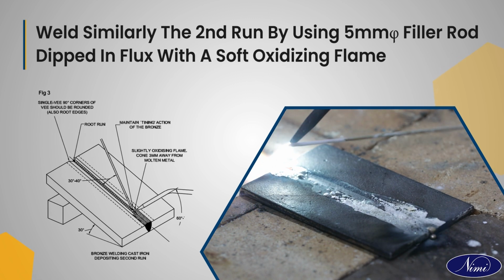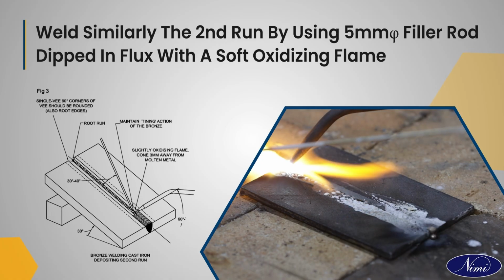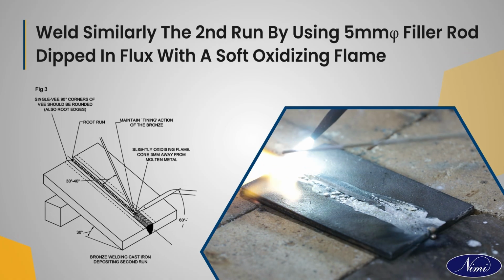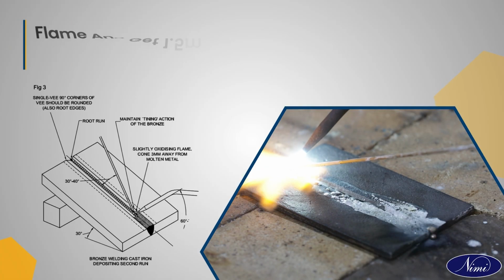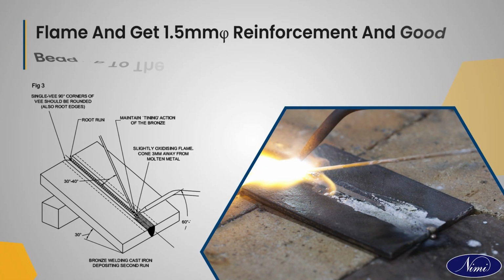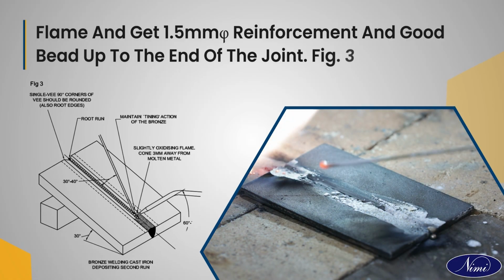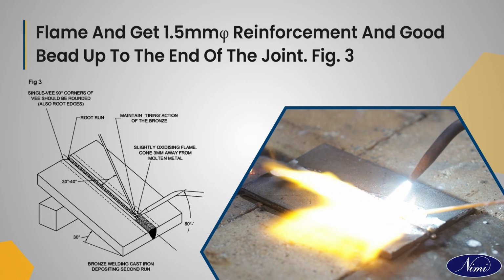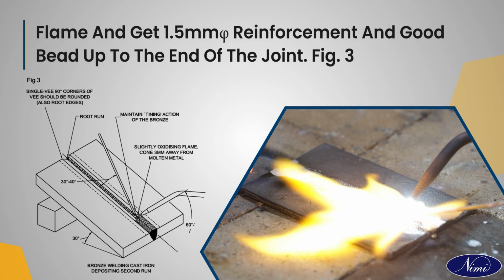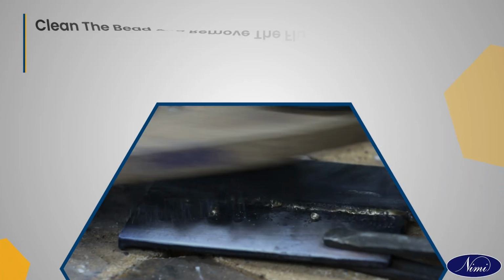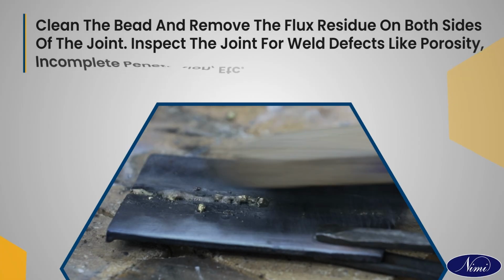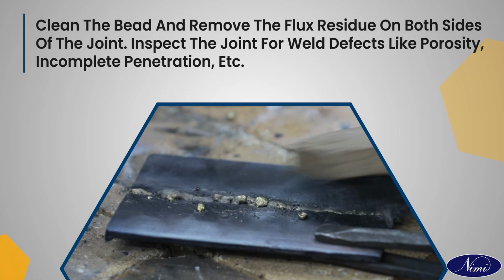Weld similarly the second run by using a 5 mm filler rod dipped in flux with a soft oxidizing flame, and get 1.5 mm reinforcement and a good bead up to the end of the joint. Figure 3. Clean the bead and remove the flux residue on both sides of the joint. Inspect the joint for weld defects like porosity, incomplete penetration, etc.